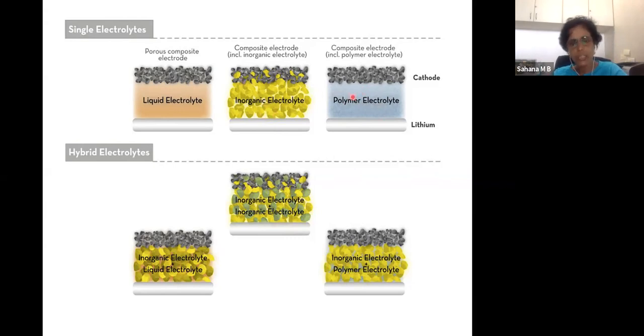So we need to have a mixture or hybrid of inorganic and polymer electrolyte. So this is a hybrid electrolyte. Basically, what we have here in the center portion is a hybrid of inorganic electrolyte and liquid electrolyte. Here we reduce the quantity of liquid electrolyte so that the safety concerns go down, but still you will have a safety issue. So only the percentage of liquid electrolyte usage is reduced.